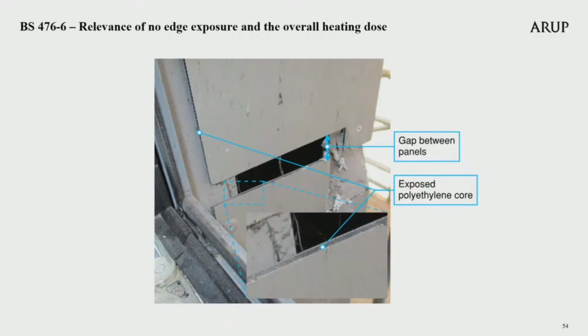The test setup is designed to prevent heating through the cut edges of the test specimen. For a composite material, therefore, such as ACM, it would mean the outer aluminium surface is heated first, and the products of combustion from any other material behind it, should they receive sufficient heat, together may cause a temperature rise in the chimney. This is why it is important to understand how much heat energy is applied to the sample in this standard test, which has a duration of 20 minutes.